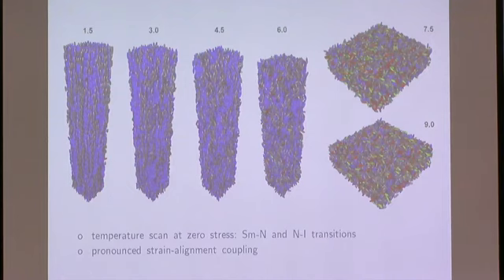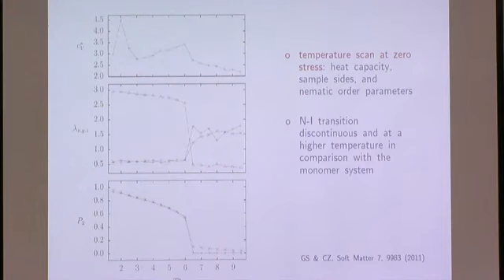And okay, to try to be a bit more quantitative, we can also plot the simulation box size as a function of temperature. So here at 6 and something, you can see this nematic-isotropic transition very clearly. And this is also accompanied by a change in P2, the global order parameter, versus temperature. You can also see a nice jump here. So this transition appears to be still discontinuous, although in many experiments a rather smooth dependence is seen.